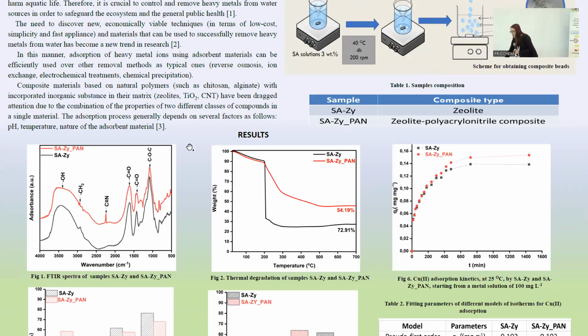First, I would like to speak about the characteristics of the beads. In the first picture, we see the FTIR spectra, and in both samples, we can see the characteristic peaks for the alginate, and in the composite sample, we can see the cyano group, characteristic for the polyacrylonitrile, sorry. The next step is the thermal degradation.